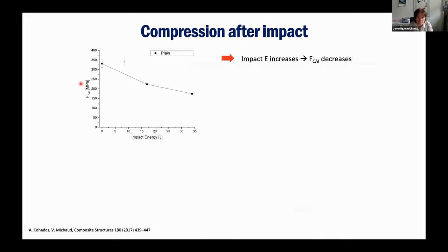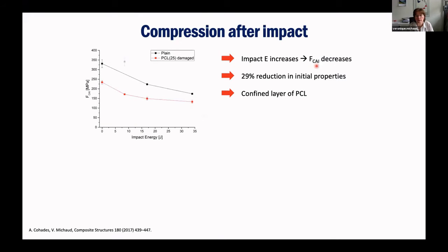And the force, so it's actually the stress, the maximum stress of this compression after impact. If you have a plain composite that we made the same way, we had a value around here, so it decreases, of course, because of the damage after impact. If we took our composite, we saw that we have a reduction in initial properties. We knew it because the material is a bit weaker, and we had all the toughness issue. So we were here, but after healing, what we found,